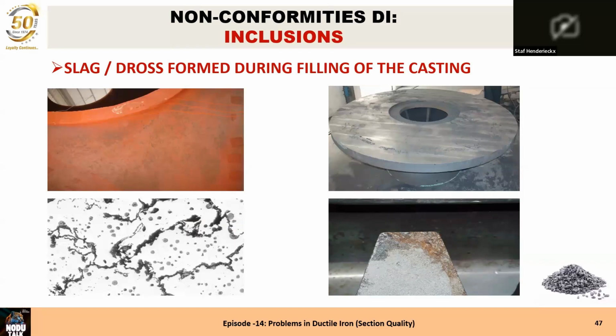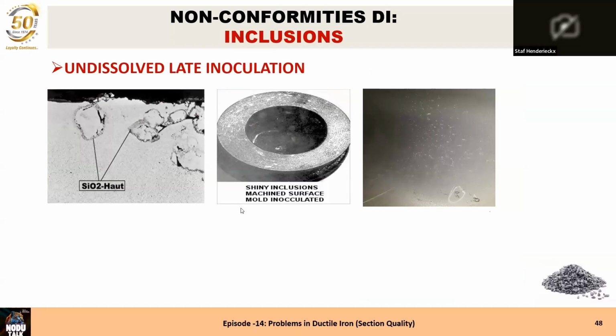At the right side top, you can see it appeared after the machining, and the left side bottom, that's when you see it under the microscope. Dross is always a long extended indication of magnesium silicon oxide inclusions. The rest of the casting, the nodules are perfect, but you see the dross there in between. Right bottom side, that was a casting with a lot of dross, and that's broken to show it, and you see again that it's the dross that was going to the top of the casting. Yeah, undissolved late inoculation.